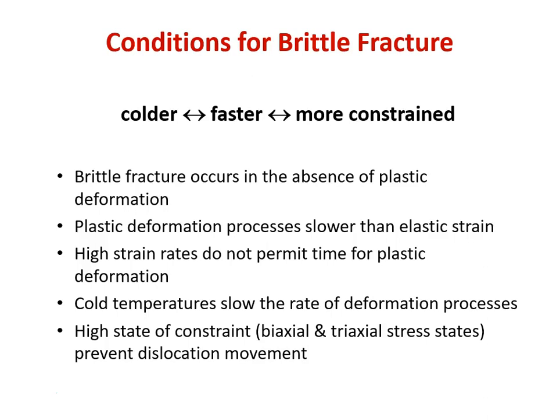More constrained refers to the number of different directions from which we're loading the material. We talked about the center of those necked areas on a uniaxial tensile sample in the case of a metal being in a triaxial stress state. So the more different directions in which we apply, especially a tensile stress, the more difficult it is to move a dislocation. We have more tensile stress, we have less shear. So if we're loading a material from only one direction, like we do in our uniaxial tensile samples prior to necking, they might be fairly ductile. If we grabbed it from the sides and we yanked from the top and the sides at the same time, we'd see that we got far, far less plastic deformation. It wouldn't elongate as much and it would fail much sooner and in a more brittle manner. So that's what the state of constraint means.